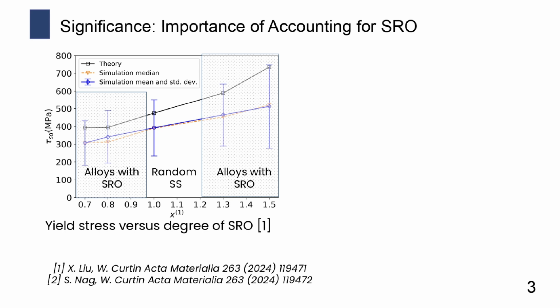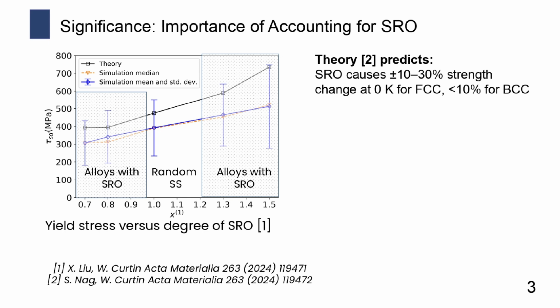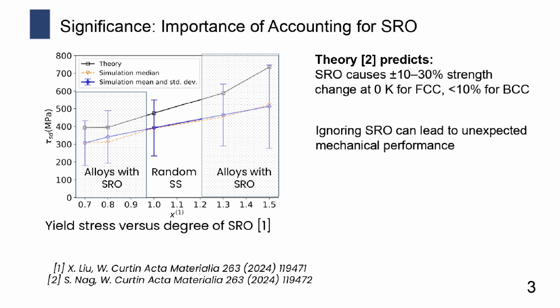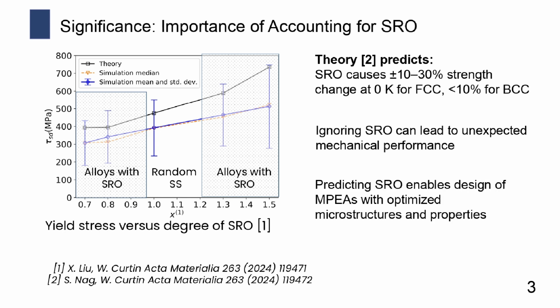As this graph shows, the strengths can be changed by the presence of short-range order in these complex systems. Short-range order can either increase or decrease strengths by up to 30% in the FCC crystals, as predicted by this theory. And ignoring short-range order means not only being inaccurate, but also can lead to unexpected failure in materials, as well as missing the opportunity to develop more reliable and strong alloys.